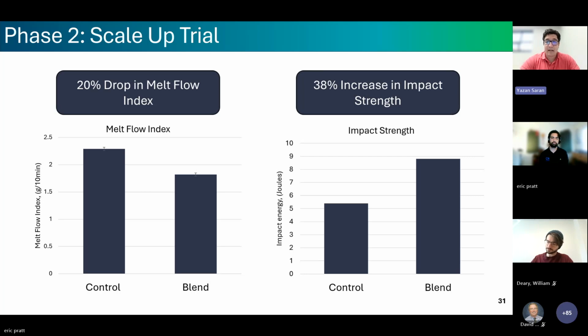Our test showed that our blend had a melt flow index value of approximately 1.8 grams per 10 minutes, which is a 20% drop from the baseline control polypropylene samples, which tested at 2.29 grams per 10 minutes. But it was still well within the range of values that we deemed acceptable and processable.